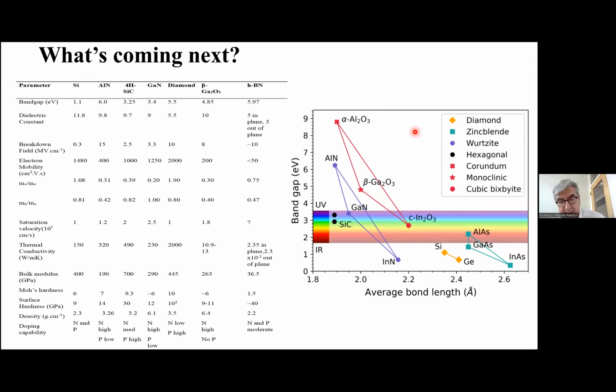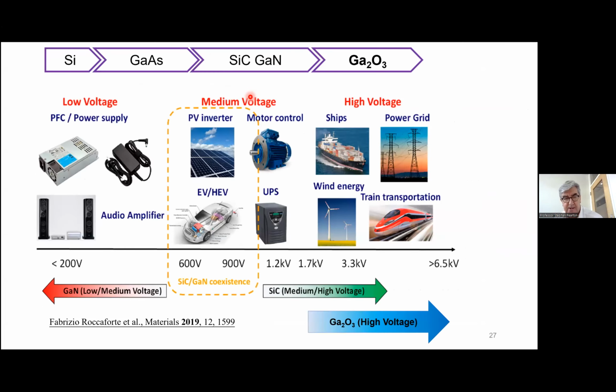So what's coming next? The so-called ultra-wide bandgap semiconductors. The candidates are high aluminum content AlGaN, so the end composition would be aluminum nitride itself, band gap of 6 eV. There's diamond, there's gallium oxide, and there's boron nitride. So which of those looks the most promising right now? My own opinion is that gallium oxide looks good, for reasons I'll enumerate in a second. So go back to this plot from Roccaforte. You would be extending the applications for high voltage out beyond what silicon carbide is capable of.